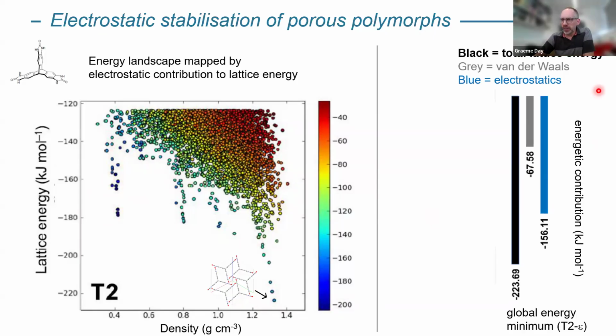And another way of showing that is to then look at the contributions here for that global energy minimum, close packed structure. This black bar is the overall lattice energy. In blue here is the electrostatic contribution, and we also have a reasonably good contribution from van der Waals interactions, the sort of generic interactions which stick molecules together.